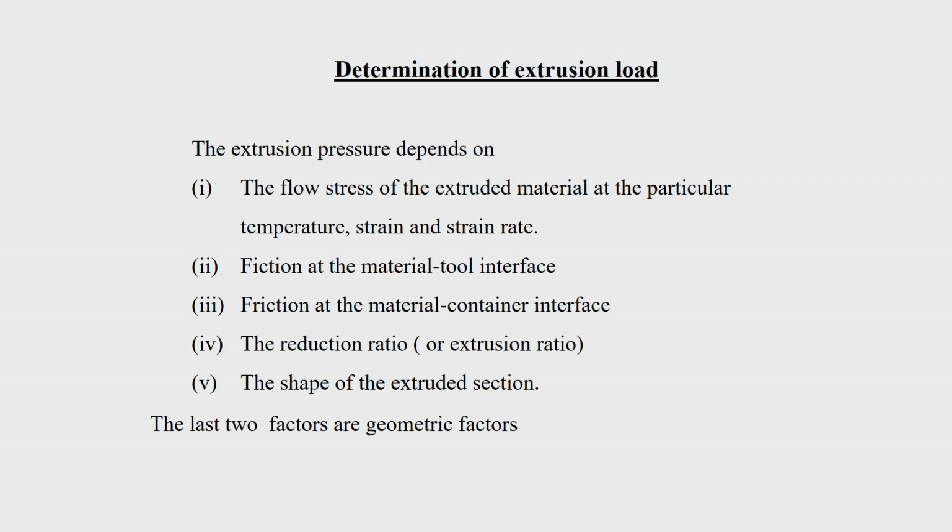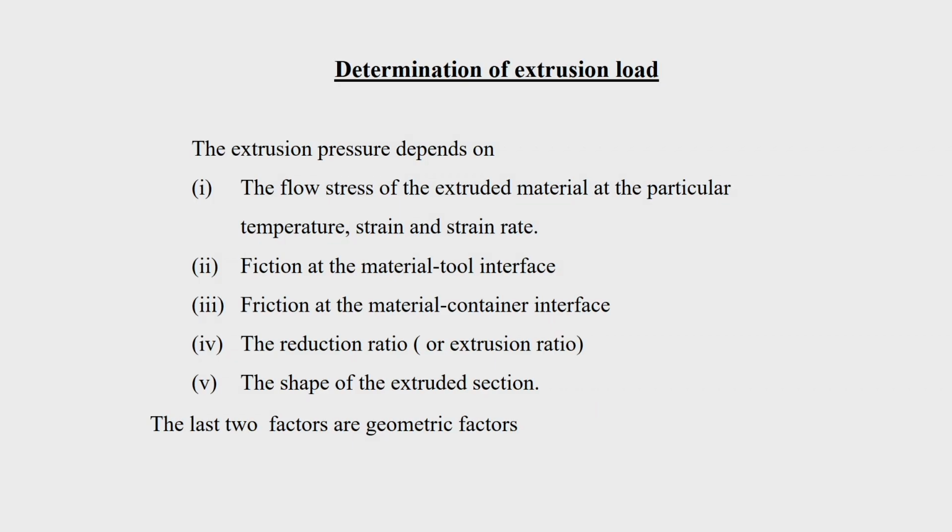The extrusion pressure, or the pressure required for the extrusion process, depends upon the flow stress of the extruded material, and the flow stress in turn depends upon the temperature of deformation, the strain and the strain rate. If it is at a higher temperature, naturally the flow stress will be lower, but there is a strong dependency on the strain rate, because strain rate sensitivity comes into picture. So, though flow stress will be lower, that is there. And then it also depends on the friction,